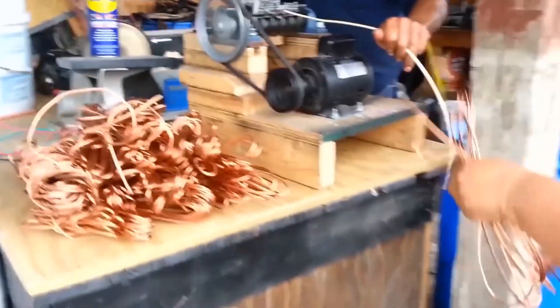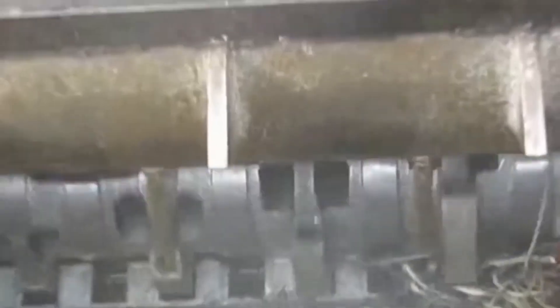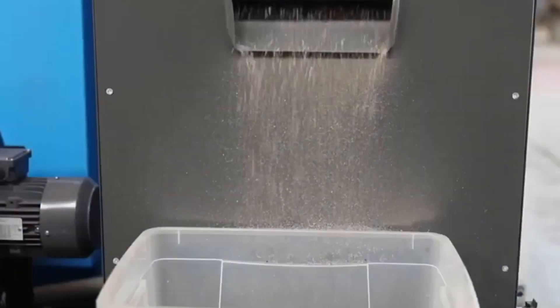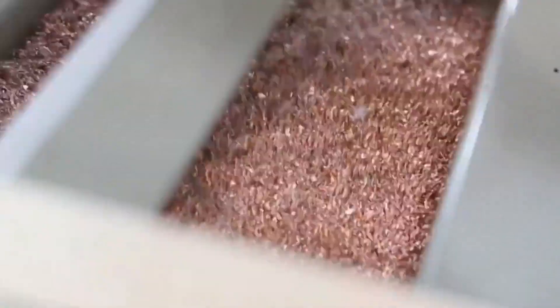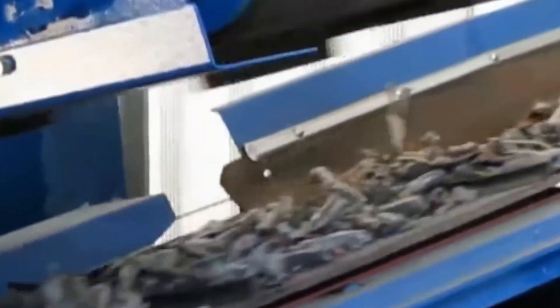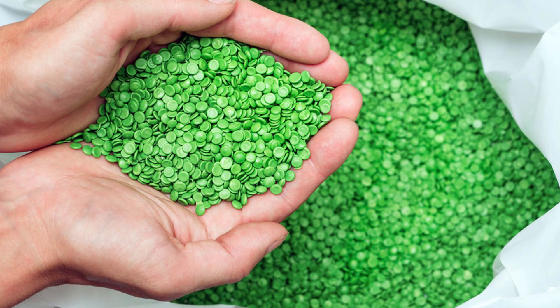When you're dealing with big volumes like piles of telecom cable, it takes more than one machine — that's where shredding systems come in. One popular setup is the QD600, a mid-sized machine that can process up to 800 kilos of wire every hour. A conveyor belt feeds the wires into a shredder, which chops everything into smaller chunks. Then a magnet pulls out bits of steel or iron before the mix heads to the granulator, where airflow and vibration tables use light wind currents and motion to lift off the plastic and let the heavier copper fall through. The separation is so accurate, you can get up to 99% pure copper, leaving two neat piles: clean copper granules ready for melting, and recovered plastic that can be sold for use in construction or car parts.